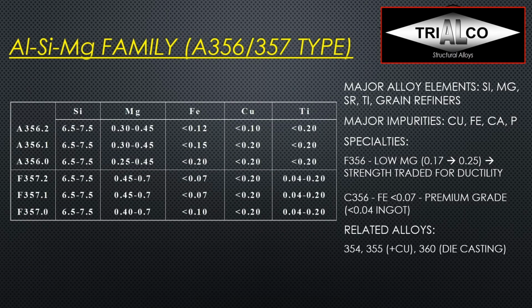If we look at this family now in more detail, we see here two common representatives, the A356, and we see here again the chemistries for A356.2, .1 and .0. Remember .2 would be the high purity ingot, .0 is in the casting, and the F357, again the .2, .1 and .0. And we can see that the silicon is the same, and we have the magnesium as the major difference. A356 is the lower magnesium alloy, and 357 is the higher magnesium alloy. So that means in 356 I will get higher ductility, in 357 I will get higher strength.